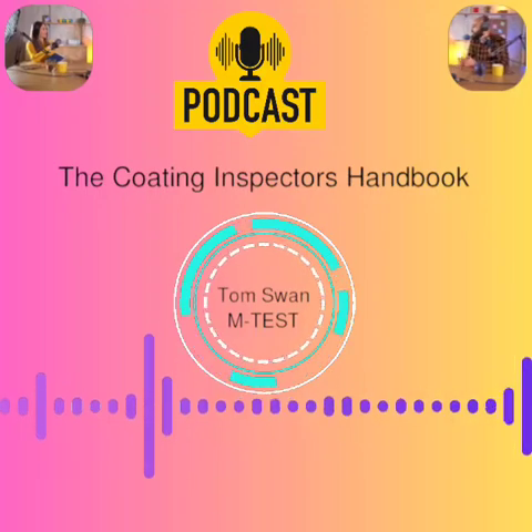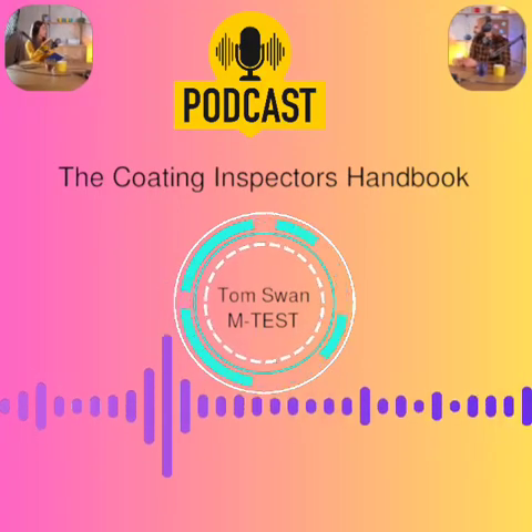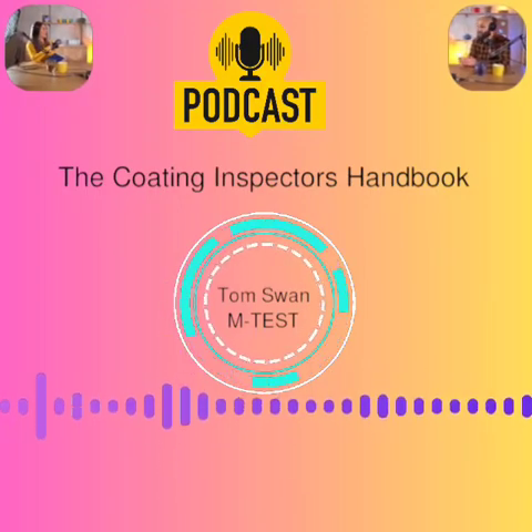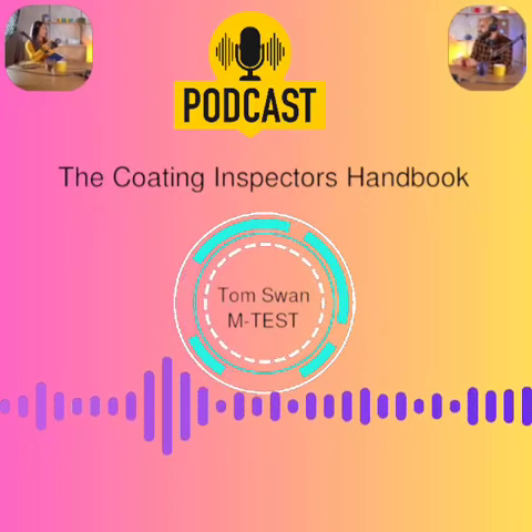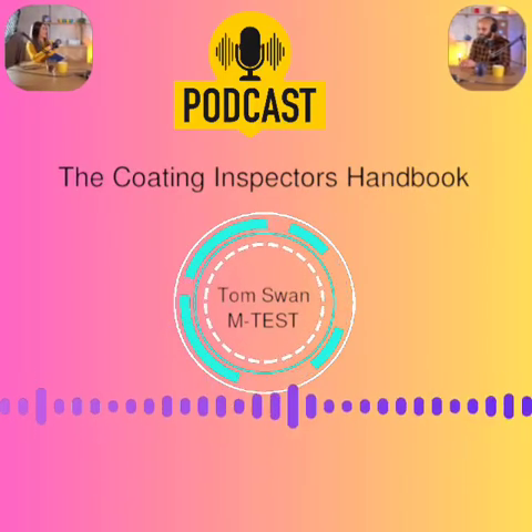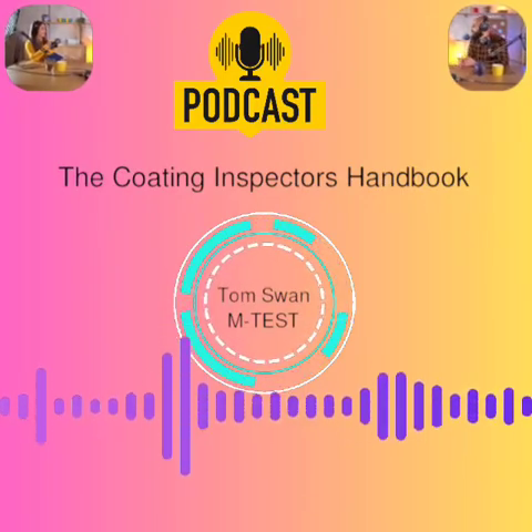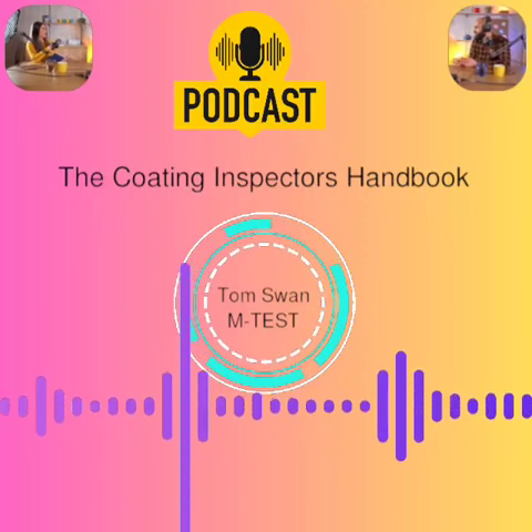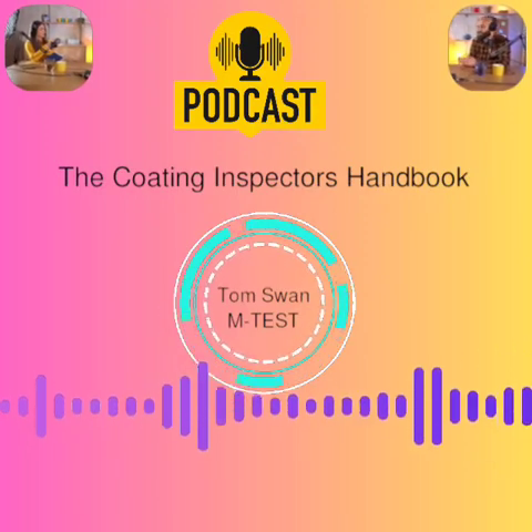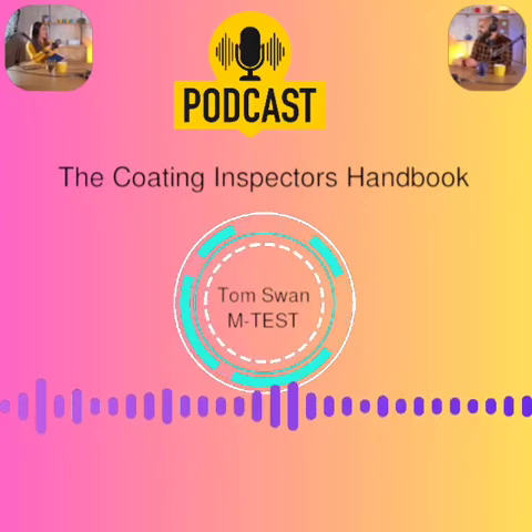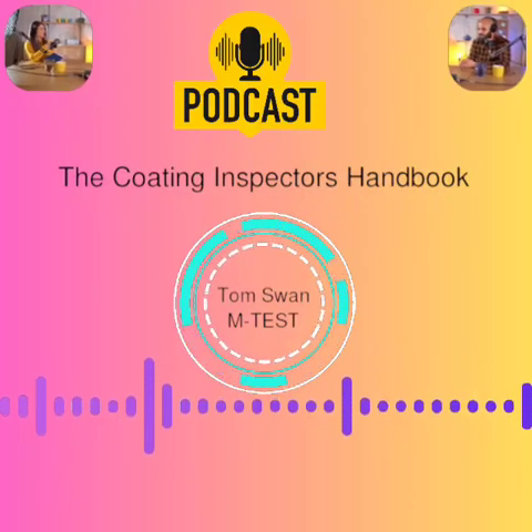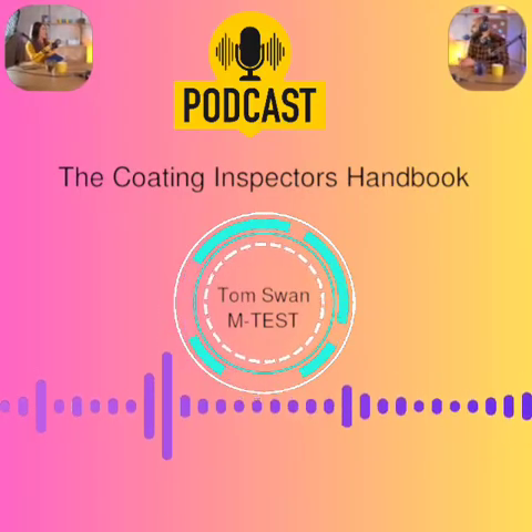ASTM D4541, pulling dollies off. Yep. Measures bond strength in psi, or cohesive strength of paint or substrate, also destructive, only when needed. The big warning: not all testers are equal. Absolutely critical. The psi value you get depends hugely on the tester model. You cannot compare results from different types, like an Elcometer 106 versus a PATTI, no valid conversion. ASTM recognizes 5 different types.